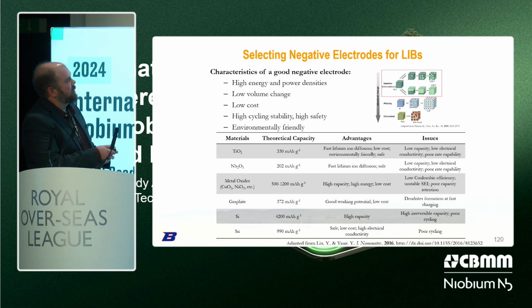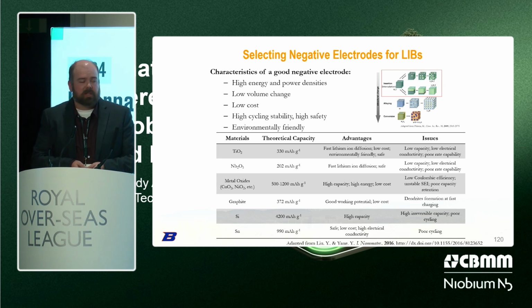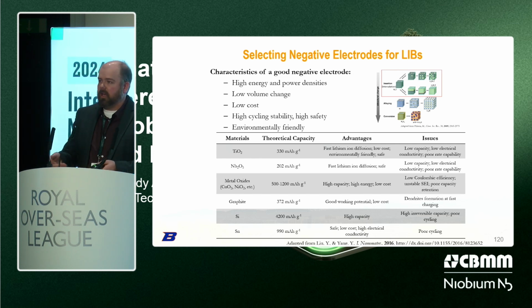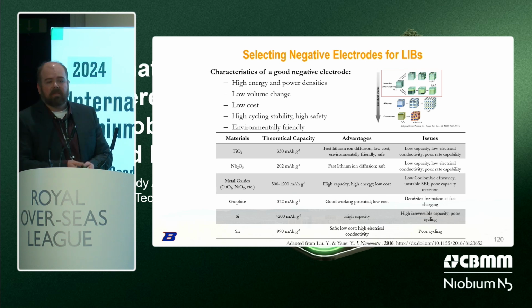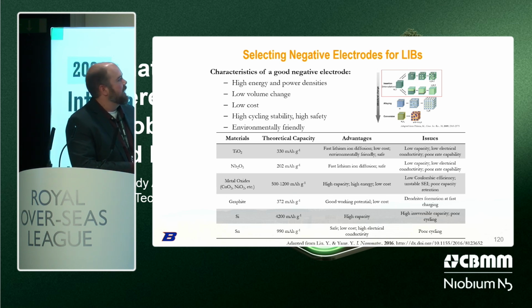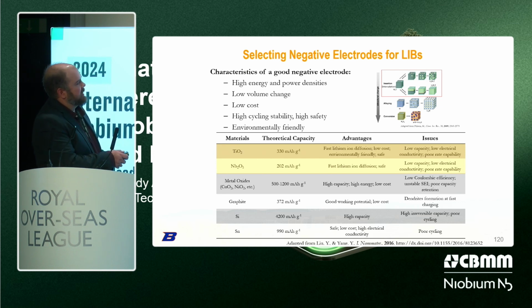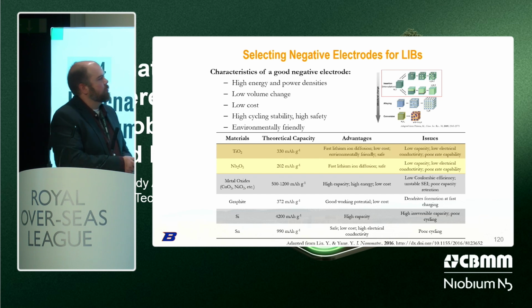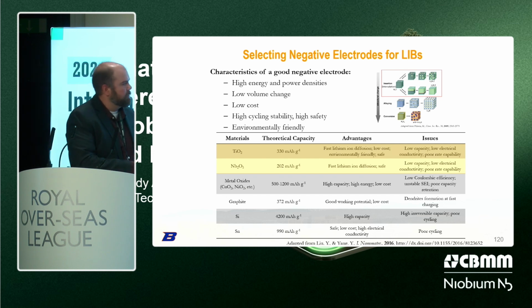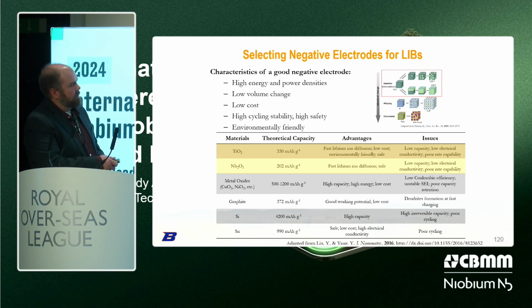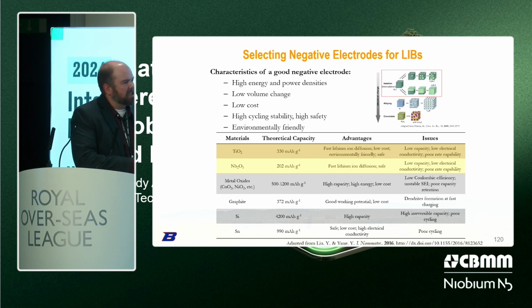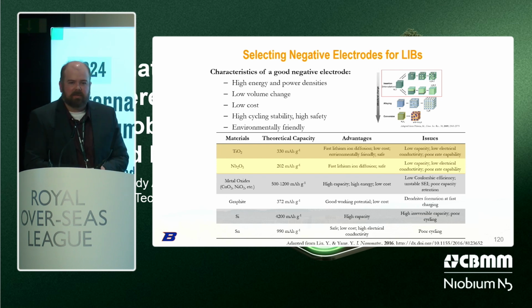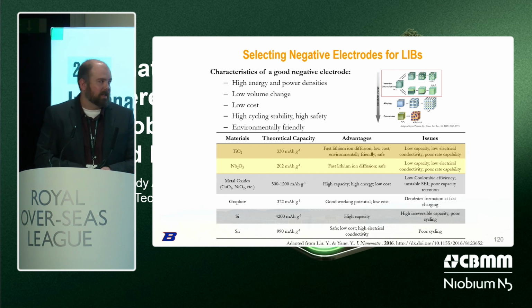If we want to select the negative electrode for the lithium-ion battery, we have to think about high energy and high power densities, and low volume changes. Is it economically a good solution for costs? Do they have high stability and are they environmentally friendly? Our group is really focused on titanium and niobium oxides with theoretical capacities of 330 and 202, respectively. They fit a lot of this parameter box I outlined, but they have low capacity and low electrical conductivity, which hinders their ability to operate in this field very often.